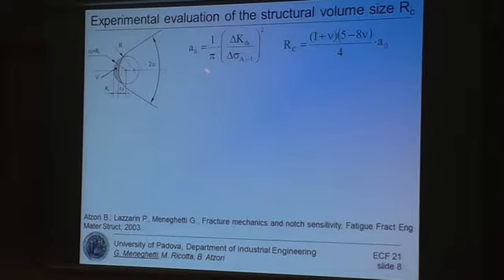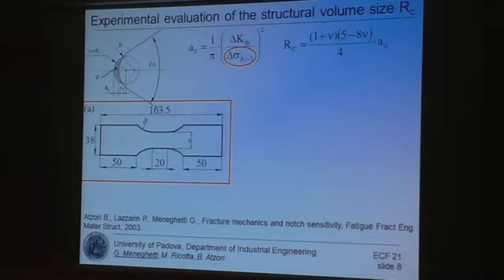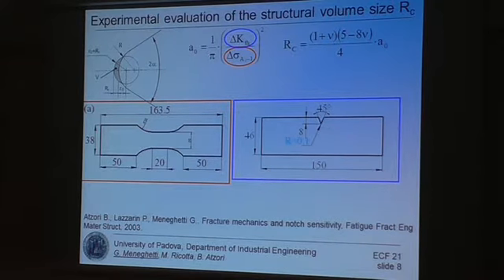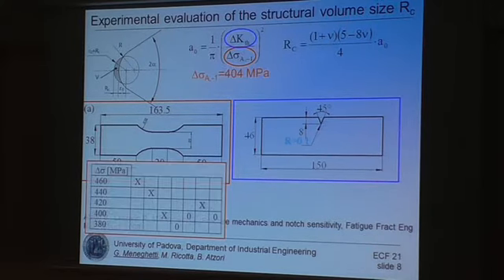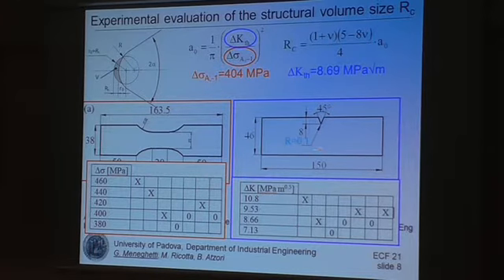Now, in order to estimate the El Haddad, Smith and Topper length parameter, you need to perform a fatigue test on the smooth specimen in order to find the material fatigue limit, and you need also to perform fatigue tests on very sharp notches in order to find the threshold value of the notch stress intensity factor. So you can see here the short staircase sequences we have adopted, where the fatigue limit resulted 404 megapascal, and here the short staircase sequence for the very sharp notch, where we found a threshold value of the stress intensity factor equal to 8.69 megapascal per square root meter. From this value, you can calculate the El Haddad-Smith-Topper length parameter and the RC value.